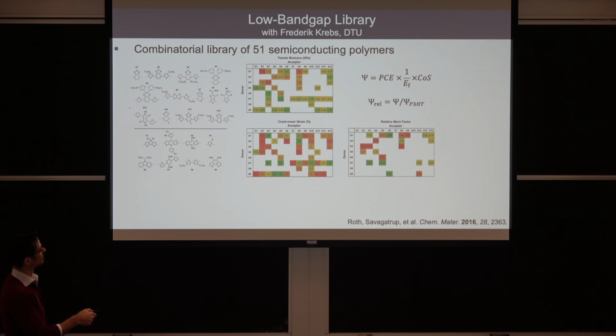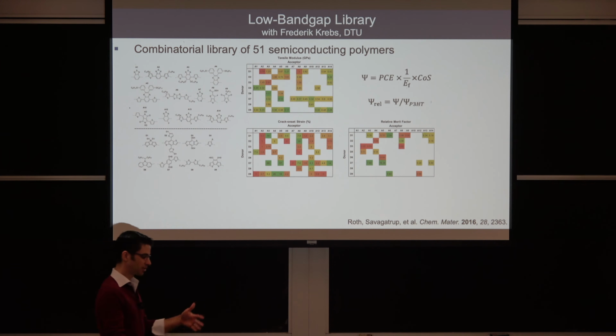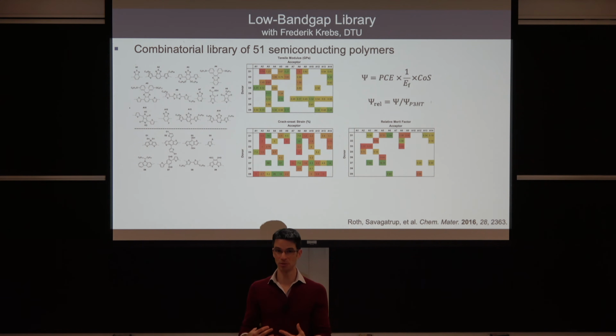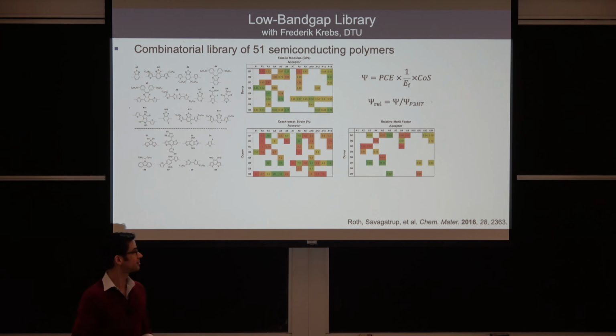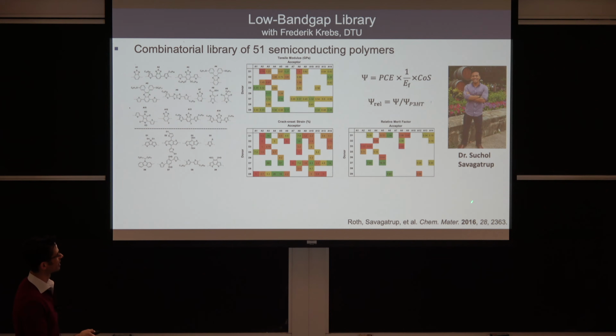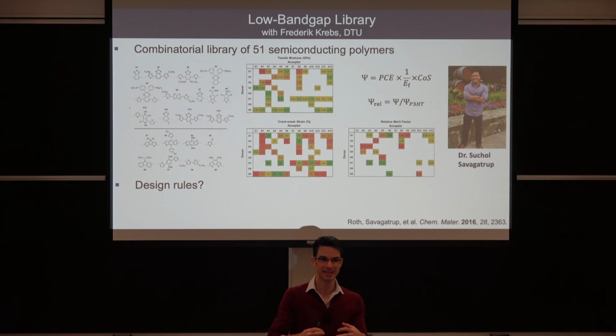So it turns out if you calculate this parameter, this merit factor, some of these materials are actually predicted to be better than P3HT if you combine knowledge of the predicted thermomechanical stability with the power conversion efficiency that was measured by the Danish group in a solar cell. This work was done by Suchol Savagatrup, who got a postdoc at MIT and is now on the faculty job market. So what are the design rules here? This brute force experiment is only really valuable insofar as we can figure out what are some characteristics that we can apply to other materials in the future.